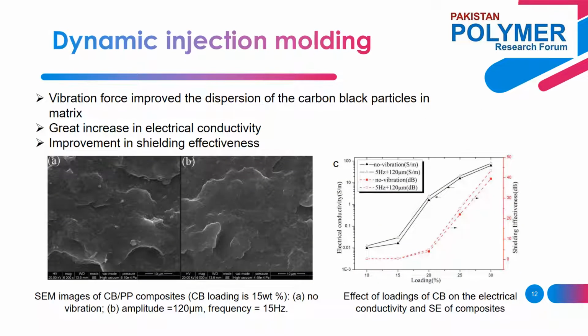Morphological analysis was performed to study the effect of vibration force on the dispersion and distribution of carbon black nanofiller. SEM micrographs are shown in figure A and B. Figure A shows the micrograph of the carbon black and polypropylene nanocomposite without any application of vibration force. It can be seen that the distance between carbon black nanoparticles is large with no vibration, and carbon black particles have no obvious agglomeration phenomena in the matrix.